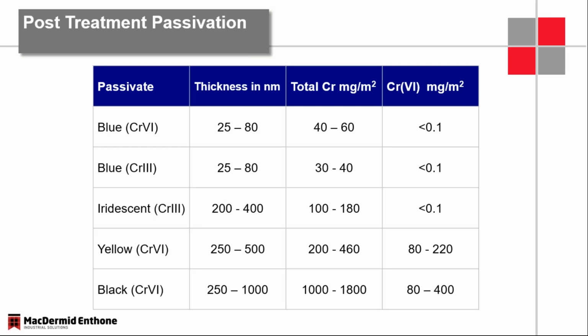And if you look at that first slide that I had, we're trying to eliminate hexavalent chrome out of the systems because they wind up in landfills at some point. And then black coatings, you can also put olive drab on there as well. You're really starting to generate some serious film thickness on a hexavalent black, almost up to 1,000 nanometers. And then because the film thickness is greater, obviously the total chromium content is going to be greater as well. This does not necessarily mean it's going to be more corrosion resistant, however.